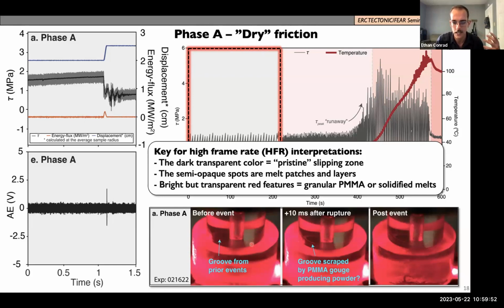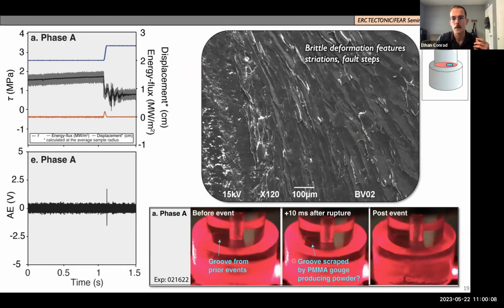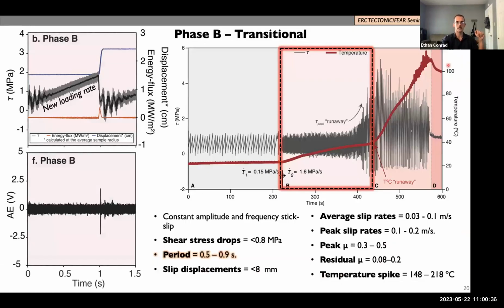And in these experiments, like I said, we see a relatively pristine surface with some groove that's kind of being formed, maybe from a small clast plowing that groove into the interface, creating maybe some powder. The pictures aren't high enough resolution to see any powder or anything. But we do have SEM images of the interface. And what we see on the interface are these brittle deformation features, these kind of striations and fault steps that you would see at an outcrop. And so here's, my mouse isn't responding super quickly, but here's these striations here. Here's some examples of what we're saying these fault steps are. And like I said, this is just taking a map view on the interface.